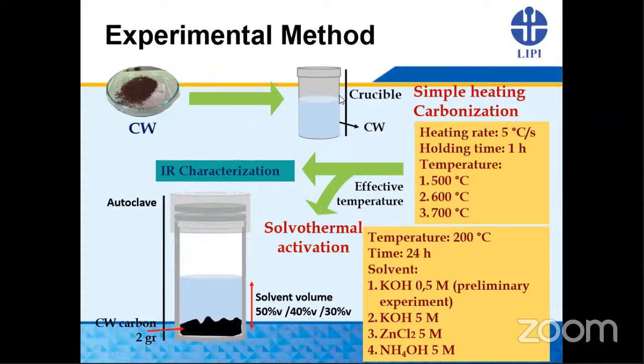The carbon waste will be carbonized here using simple heating carbonization. At first, we tried these three temperatures, and after that, we characterize the infrared properties of the carbonized sample, and also after that, we conduct the solvothermal activation using this parameter. Temperature is about 200 degrees C, time 24 hours, and we use potassium hydroxide 0.5 molar for preliminary experiment, and after that we compare using a higher molarity solvent.